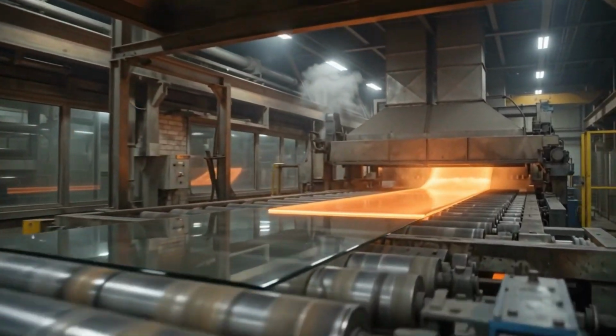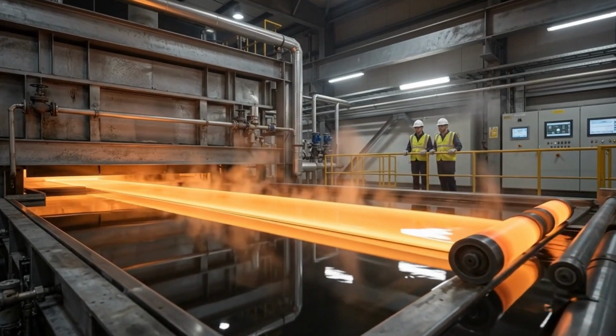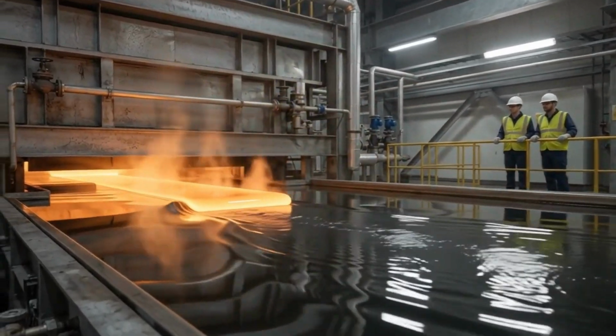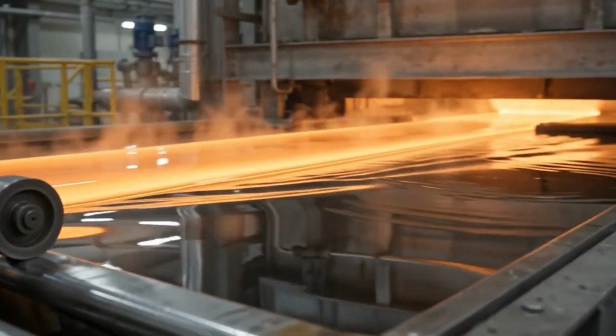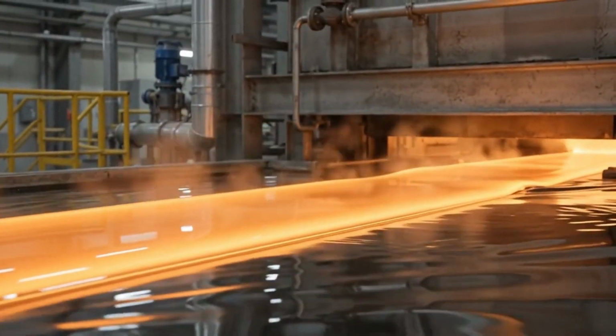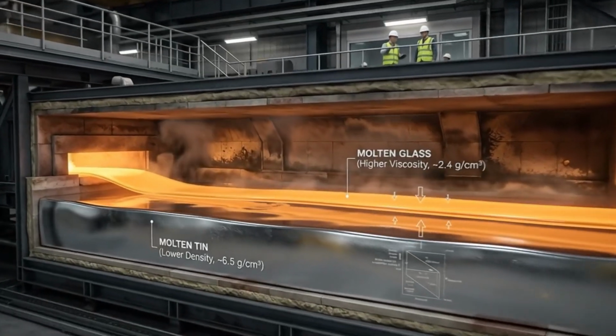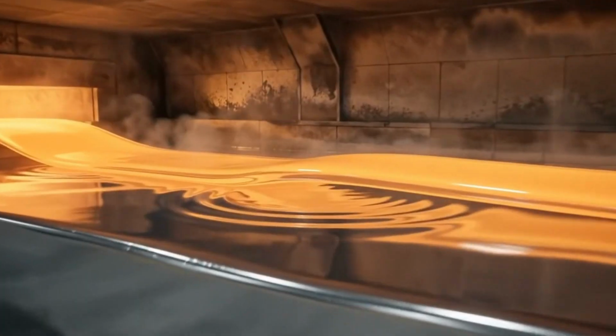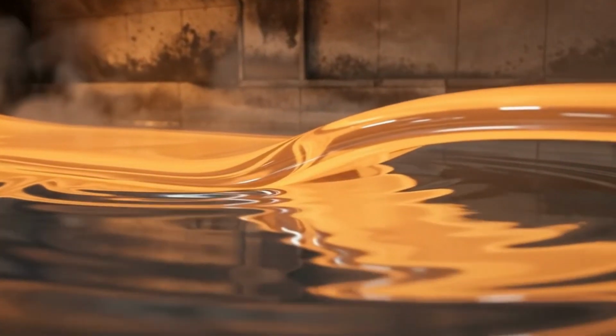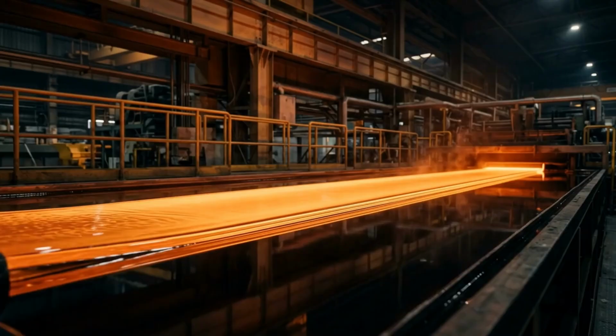And something incredible happens. Gravity naturally pulls the top surface perfectly flat, while the liquid tin creates an equally smooth bottom surface. Without polishing. Without grinding. The factory produces an almost perfectly flat sheet of glass. It's one of those rare engineering solutions where nature does most of the work.